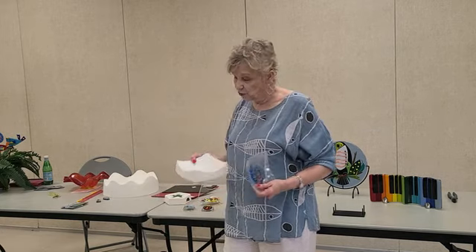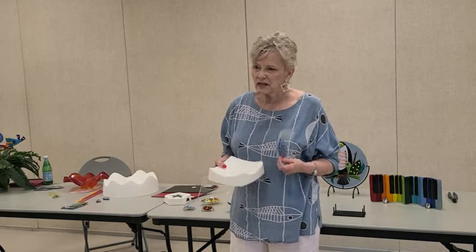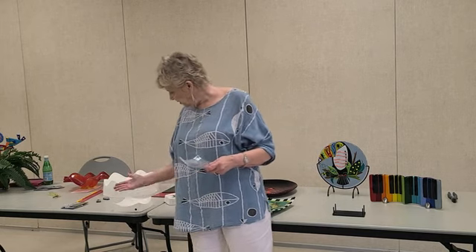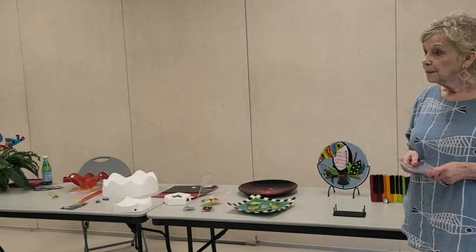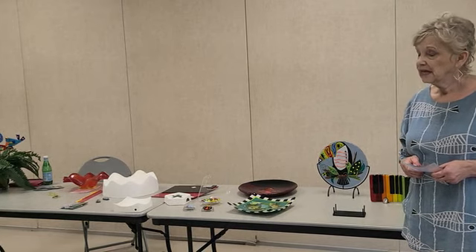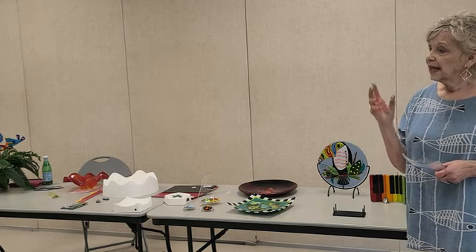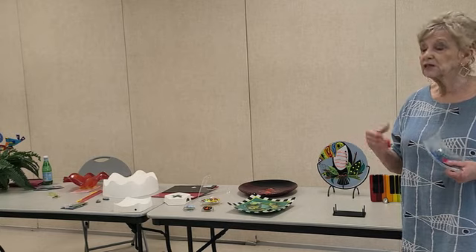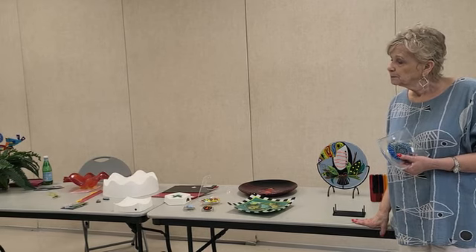They're just ceramic molds. You can use dishes, actually. If they're ceramic dishes, not glass, you can use that and make your own. You just have to make sure you have something on there so that the glass doesn't stick to it. There's something called Zip or ZYP, and I think it was originally a lubricant for motors, and you can spray it on and nothing will stick to it. Well, things will stick to it, but glass isn't going to stick to it, not at the temperatures we use.